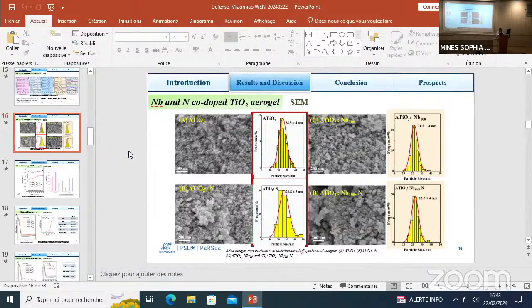And in the case of nitrogen-doped materials, you see a very strong effect. So the roughness also can be due to the calcination and reactivity of the surface in ammonia atmosphere, because probably there is some difference between the two different calcinations and the two different atmospheres, in fact.